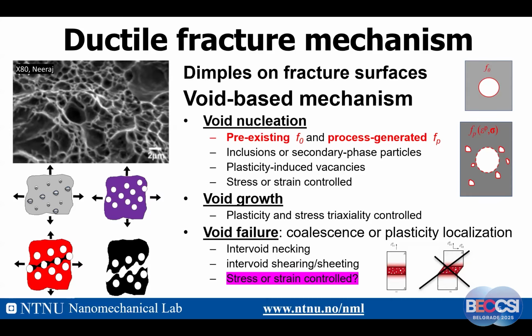And then once the voids have been nucleated, under the plastic deformation and stress triaxiality, hydrostatic stress, these voids will grow. Then at certain stages, the void growth will be stopped. So we will have void failure. That's also called coalescence or plastic localization by void sheeting. Here we have two types of loading. One is tensile, another shear. And in this talk, we will focus on tensile loading. My question is, can you guess, is void coalescence stress controlled or strain controlled? I will ask you later.